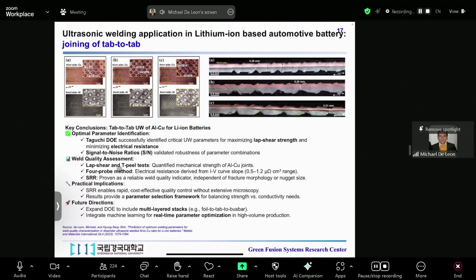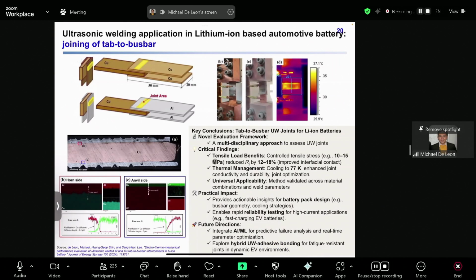For example, by applying around 10 to 15 megapascals of tensile stress, it can practically reduce the joint electrical resistance up to 18%. Also, thermal management by cooling to 77 Kelvin enhances joint conductivity and durability, along with universal applicability with other material combinations.